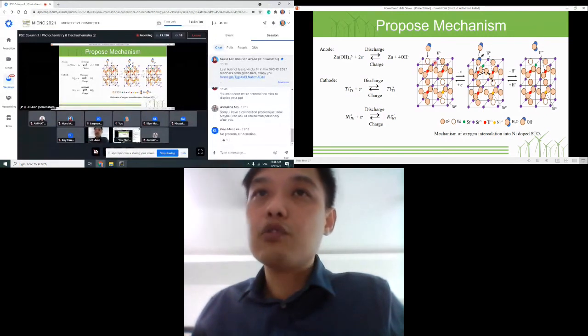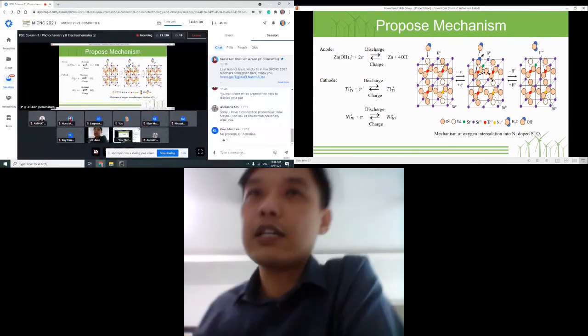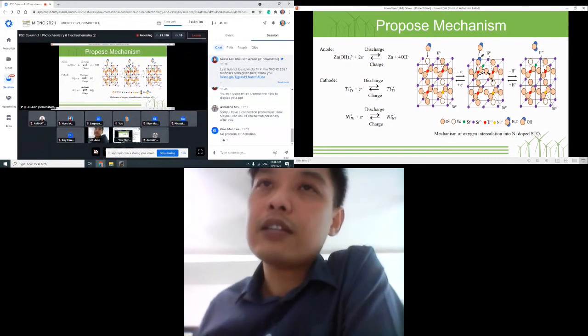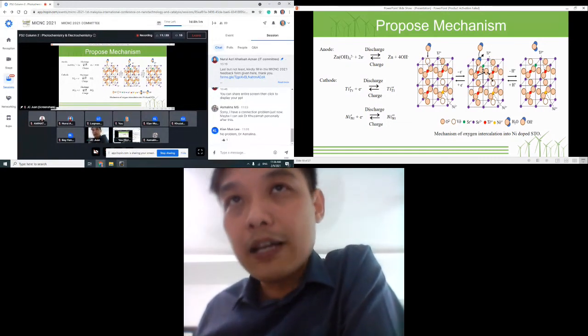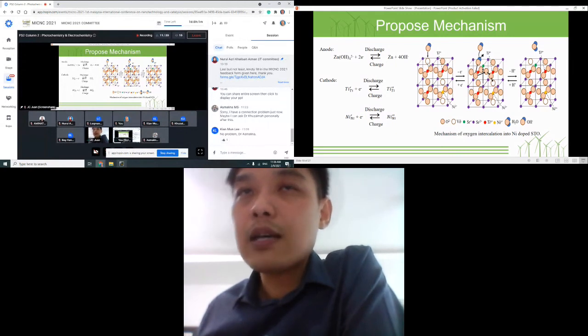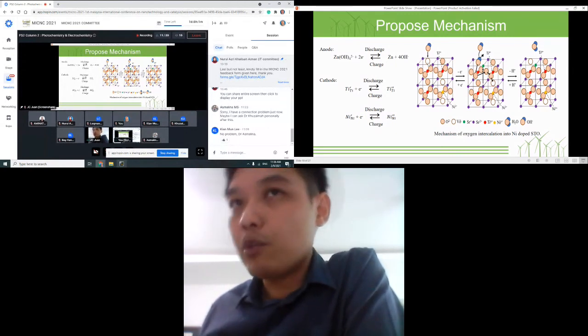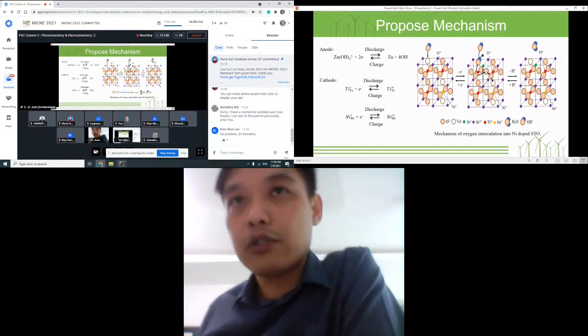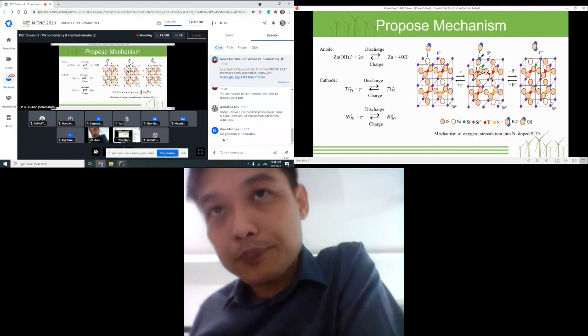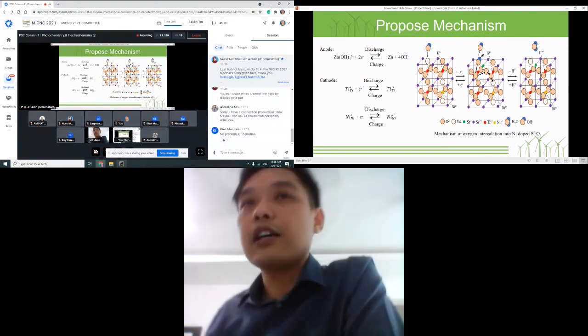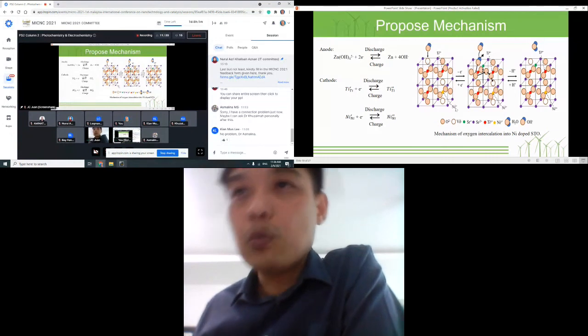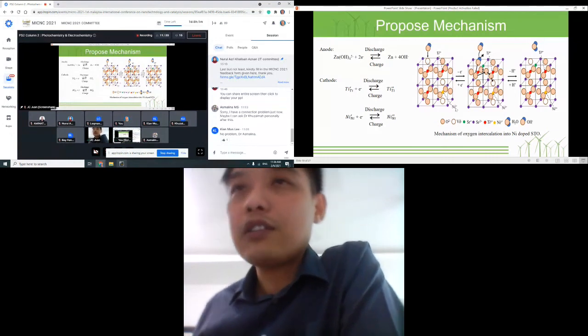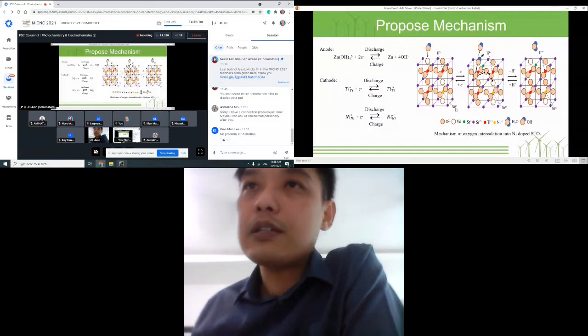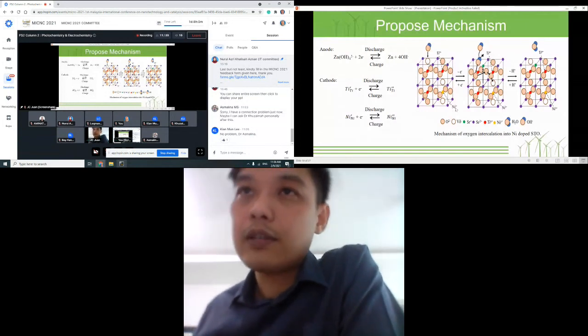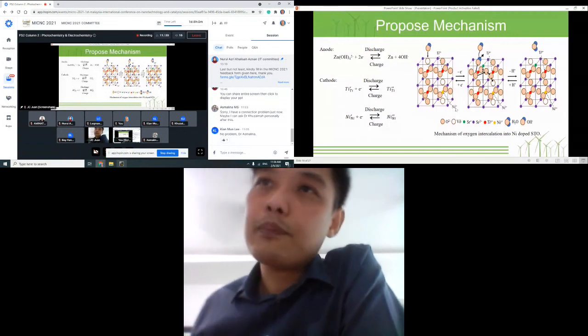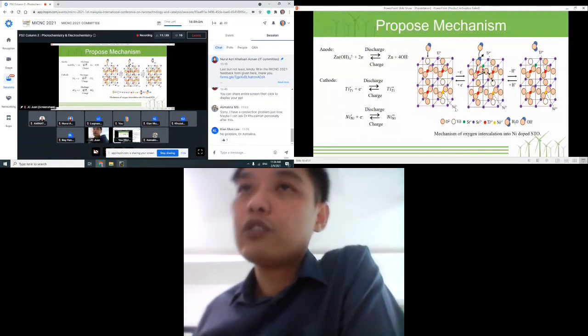For example, here there should be oxygen atoms, but these oxygen atoms are lacking. This affects the neighbor atoms. For example, Ti should be 4+, but due to this oxygen vacancy, to balance the charge, the Ti becomes 3+, because it has donated one electron to the oxygens. Similarly for nickel, it becomes nickel 2+. So when we have the charge mechanism here, because electrons have been introduced, it becomes Ti3+.